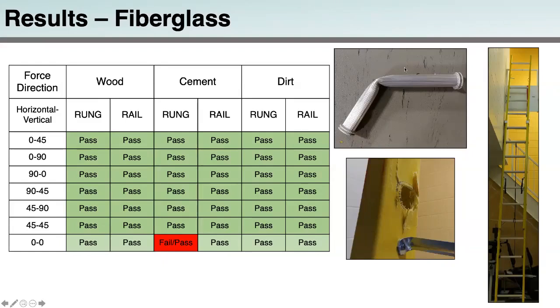This was determined to be a cumulative fatigue failure. The ladder was extended an additional 2 feet and a retest was performed on the intact rung at the new height. With the retest pass on an adjacent rung, this condition was deemed a successful pass. So this failed test was the first of the 0 straight down drop force directions tested, and it passed on all of the remaining conditions.